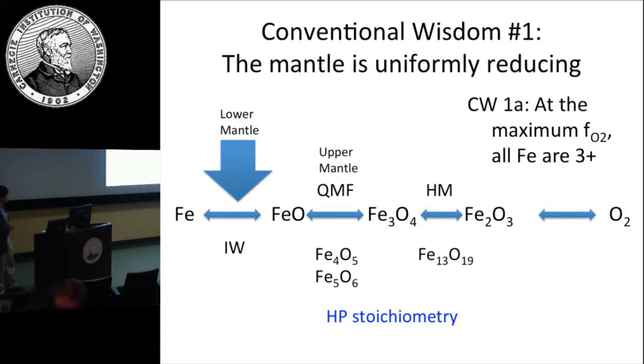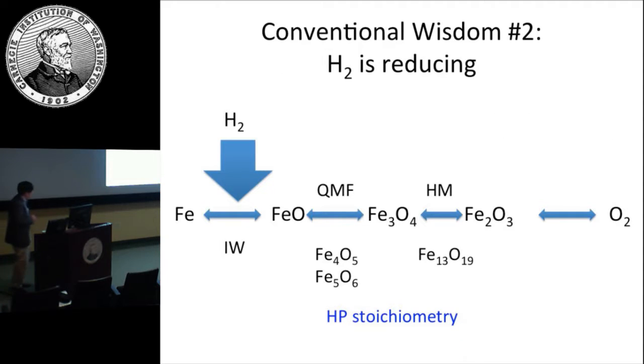Okay, now for this series, oxygen fugacity is defined by the stoichiometry of those things. So those are like buffers. Okay, and now there's new stoichiometry found, but never over this side. Okay, now the conventional wisdom number two is people think H2 is reducing. It is reducing at ambient condition. So if you put H2 and FeO together, you reduce some FeO and form some water and reduce some to that side. So it is reducing. Okay.